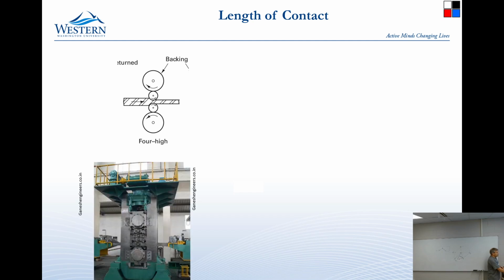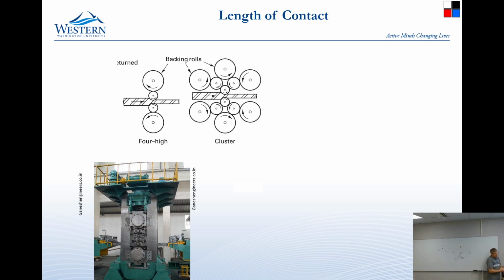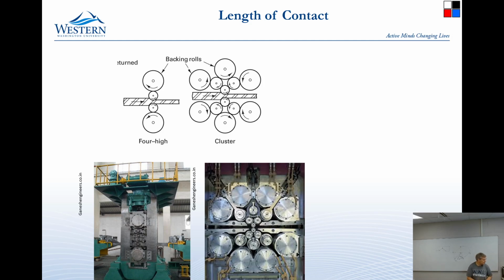And so you can do a 6-high mill where now we have a big roller backing up a little roller, backing up a little roller. Or if that wasn't enough of a cluster, we can do a cluster mill. No way! So this is what actually happens. Just to have 2 rollers, we have to have all these other rolls to back it up, because the little roll has to be backed up by slightly bigger rolls, which have to be backed up by even bigger rolls. And so there is the bearing set, just looking at it from the edge. You can see that is a lot of rollers just to support those 2.